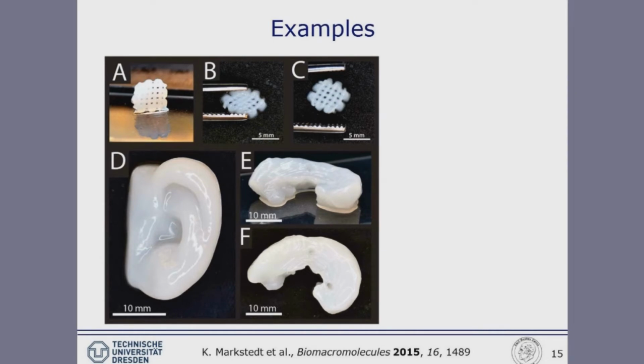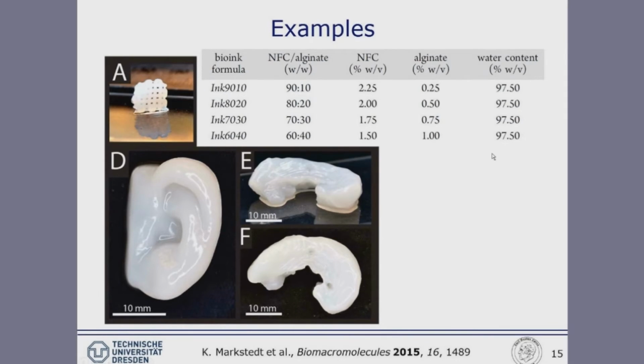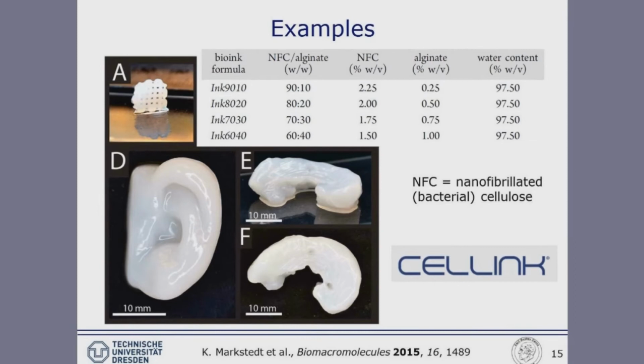This is work from the Gatenholm group from Göteborg, Sweden. They have combined, again, alginate as the basic biopolymer with bacterial nanocellulose microfibers in different concentration ranges, using very little concentrated alginate, but partly rather high amounts of this bacterial nanocellulose. And with this, they could achieve a number of different bioinks. They could demonstrate them to be suitable for different cell types. And this is one of the few bioinks which already has been commercialized by this group from Sweden.